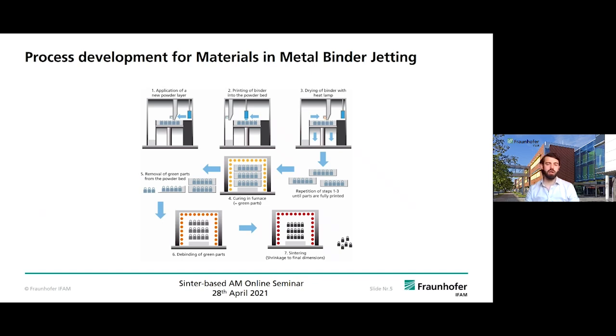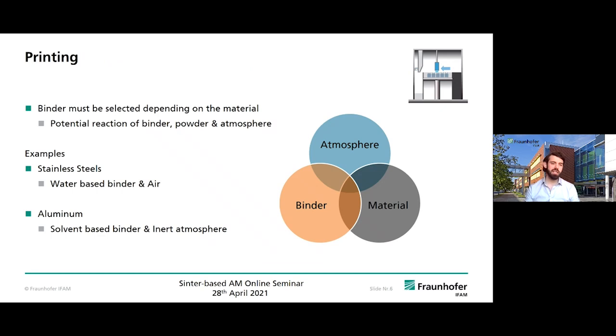Now I want to tell you, when developing materials for metal binder jetting, the whole process chain has to be taken into account. And I will go through every process step that is necessary or crucial with its specific features. So first of all, it starts with the printing process, or just before, the right selection of the binder, and that has to be selected according to the material you want to print, because there can be some interactions and reactions between the material and the binder, or even with the atmosphere.